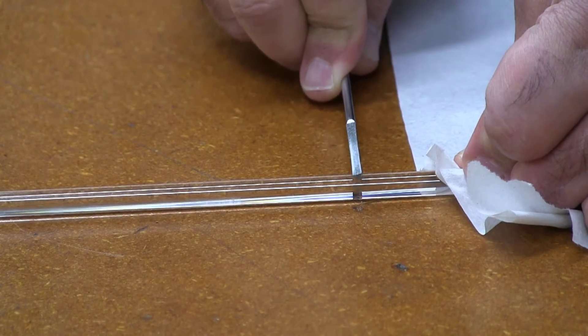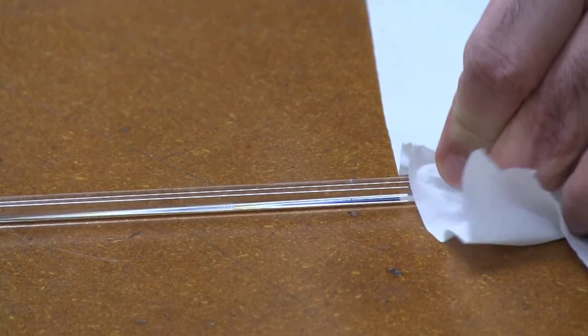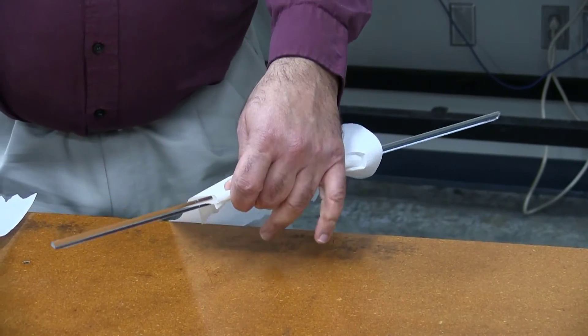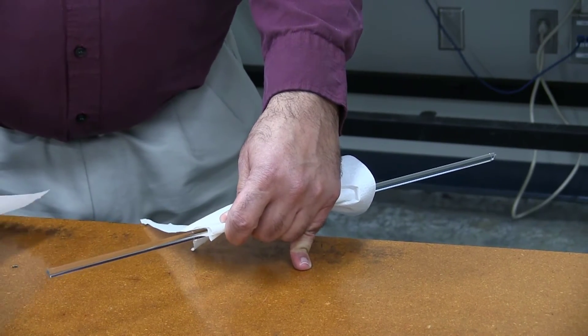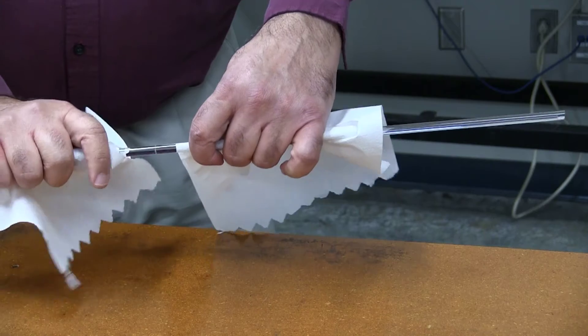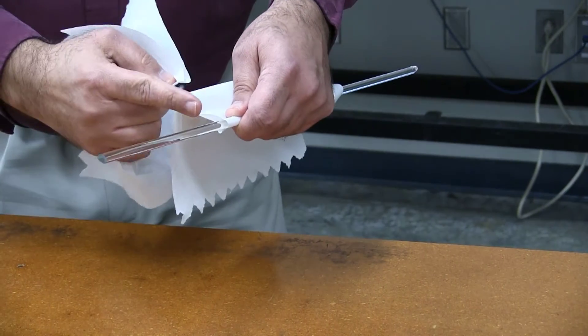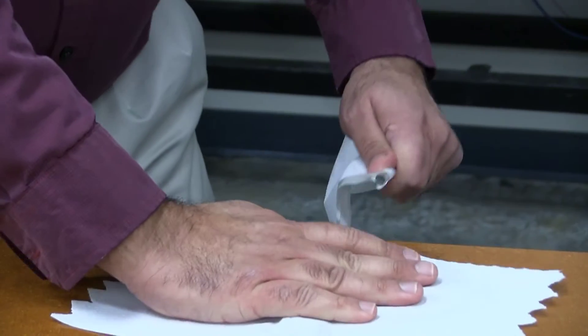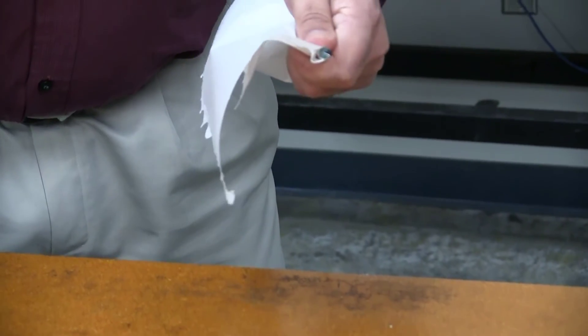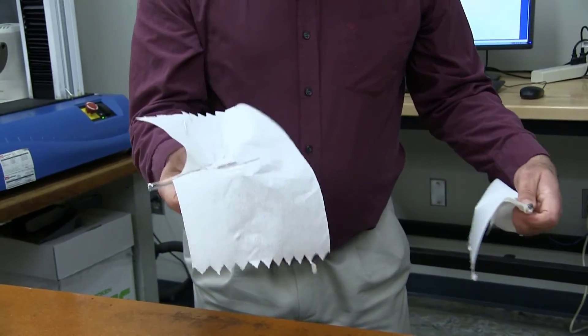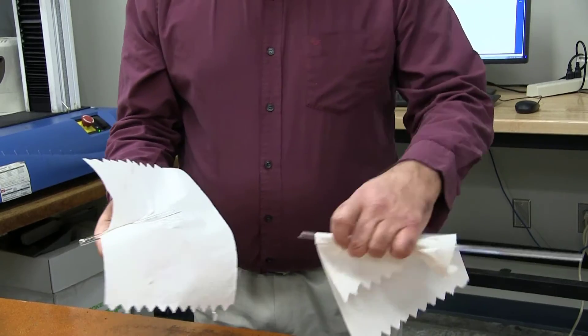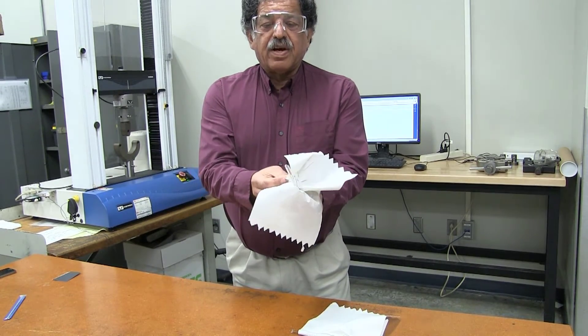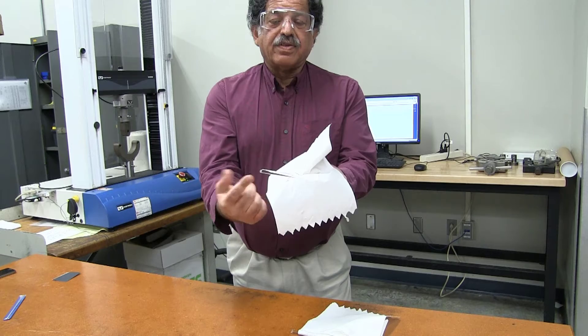Okay, so that's enough and then I'm going to put my file away here. So okay, now that we have put our circumferential notches into the specimen, what I'm going to do is I'm going to grab the end of the specimen with paper and put the area that I'm trying to fracture on the edge of the table and then just give it a sharp wrap downwards. I'm just going to go. And now what we have is a fractured end on the specimen, the specimen should be about six inches long or so. And then I'm going to clean up those shards of glass in just a few moments after we run our experiment. So here's my as-received glass specimen. It's got irregular ends, but as long as that overhangs the support, that doesn't matter.